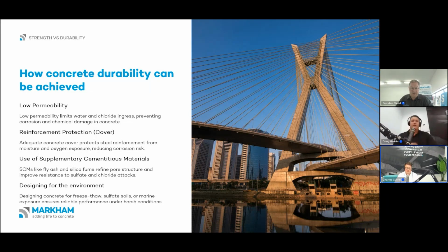Yeah, that's good, Charles. I just want to touch on what you said about the permeability there. That is really, really important when you're considering concrete. We've seen concretes that were up to 80 MPa even, I think it's the highest we've tested here for water permeability. We can still get moisture into that concrete even at that high MPa, and there's a bit of a belief out there that once you hit 40 MPa in the concrete, it's waterproof. It's not going to leak, and that's typically in the case of, say, a water reservoir or a water tank. Now, while that's not entirely untrue, that 40 MPa is going to withstand that.